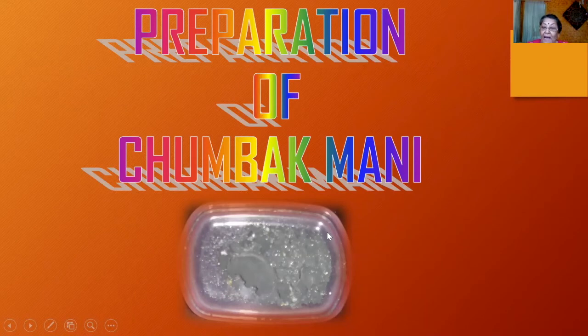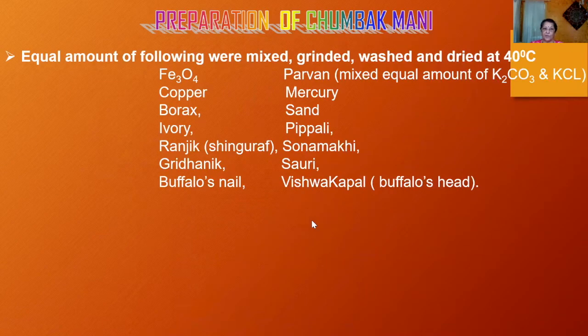As I said, our work is laboratory work, and we started preparing Chumbak Mani. The first step was that we took equal amounts, about 10 grams of each. It was nicely washed, dried and ground. Then we put all 10 grams of each into an alumina crucible. We didn't use others, only alumina crucible. And these are the ingredients.